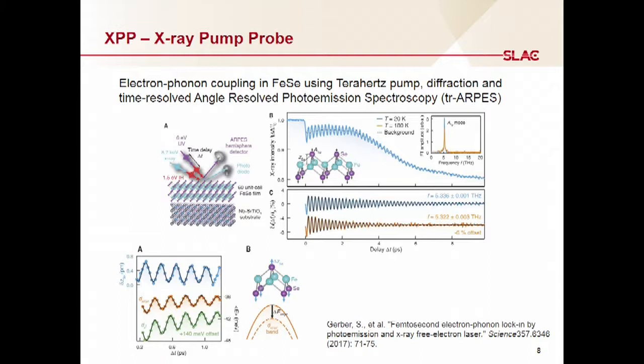And then you probe the electron band structure with time-resolved angle-resolved photoemission spectroscopy, ARPES. ARPES doesn't just look at the electron energies, but it also looks at the electron momentum. Then you can try to see if there's this electron-phonon coupling that helps to amplify the effect which you see, which can lead to superconductivity.